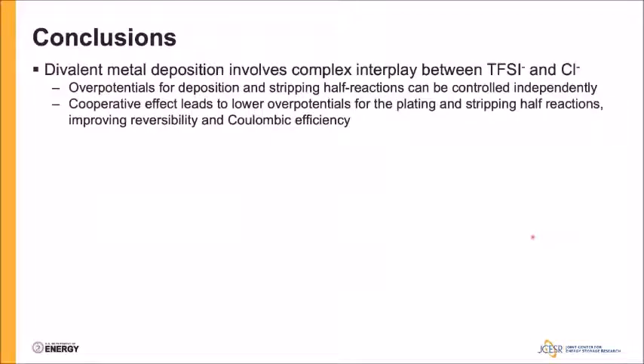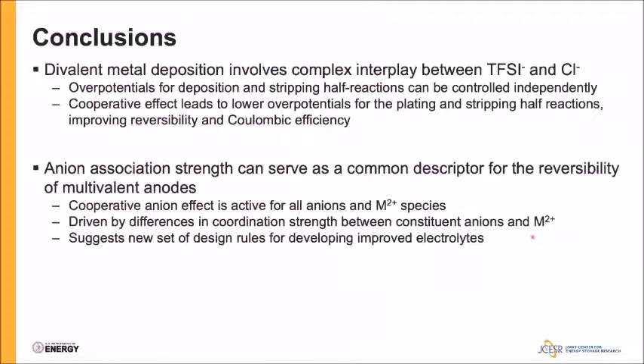So to conclude, we've shown that divalent metal deposition can involve a complex interplay between the different anions present, highlighting specifically the TFSI chloride system, where the overpotentials for the deposition and stripping half reactions can be controlled independently based on the specific anions, and via their cooperation results in lower overpotentials for plating and stripping and improvements in Coulombic efficiency. We've shown that anion association strength can serve as a common descriptor for reversibility of multivalent anodes, where this effect appears to be active for all of the anions and divalent cations that we studied in this work.